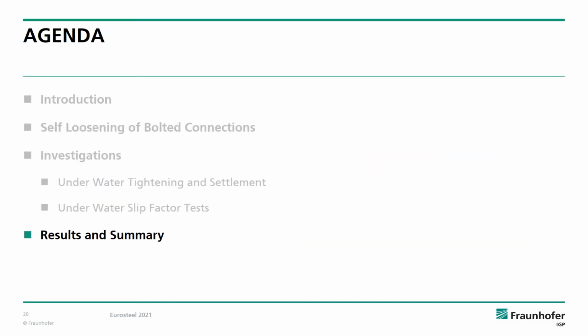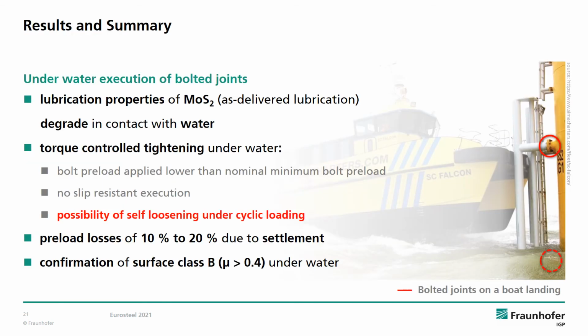Let's have a look at the results. You can find all the single graphs and diagrams in the actual paper, so what I'm going to do right now is to give you a short summary of what we found out. As you already know, lubrication properties of molybdenum disulfide degrade in contact with water, and for bolts tightened by torque, this means that the nominal minimum bolt preload could not be reached. The implication for our boat landing bolts is that even though they might have been designed as slip-resistant connections, they presumably have not been executed as such. Under cyclic loading, self-loosening might thereby be possible.